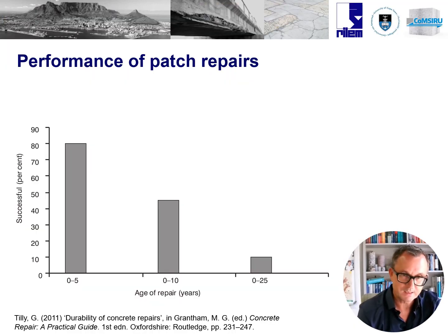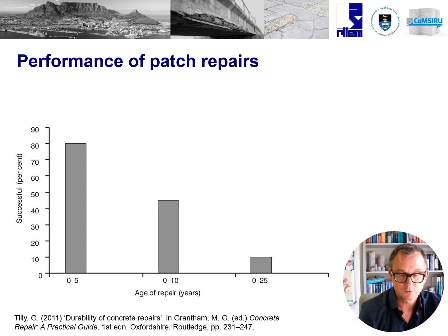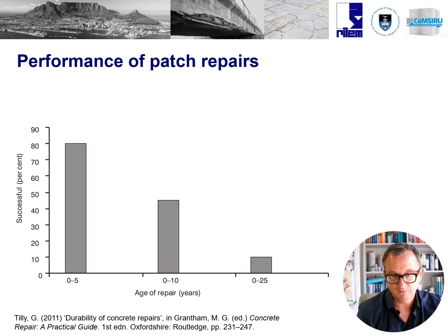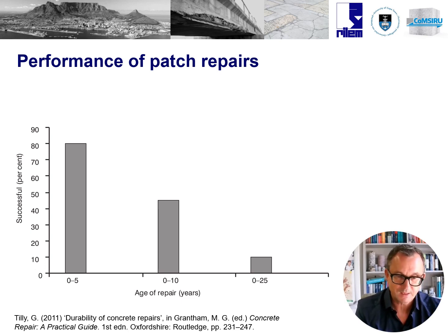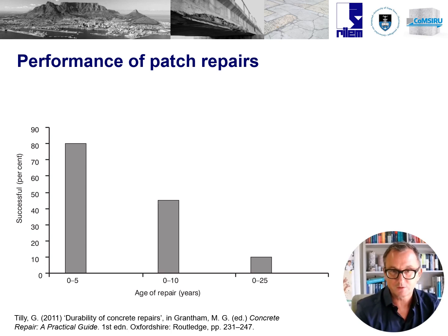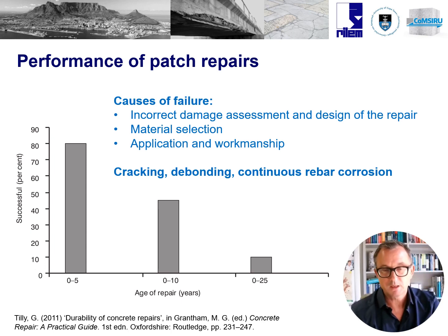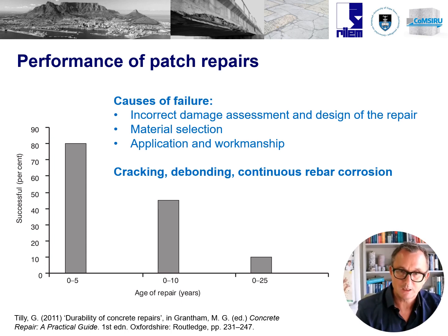Now this process of patch repair is relatively simple, but the problem is that the performance of patch repairs is typically quite bad. From literature, Michael Grantham and I investigated the performance of patch repairs in service, and most patch repairs fail after a period of about 10 years. Even though this is a very simple process, there are factors that affect performance, and if they do not perform as intended then you've wasted your money, your time, and possibly have not achieved any additional durability. The causes of failure typically are incorrect damage assessment and design of the repair, the selection of materials, and the application and workmanship.